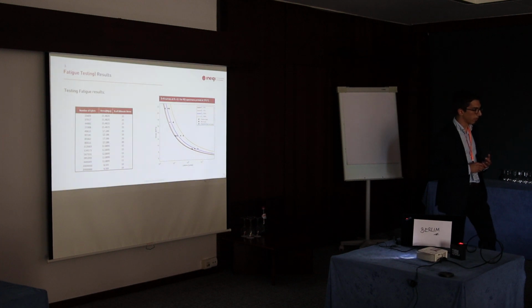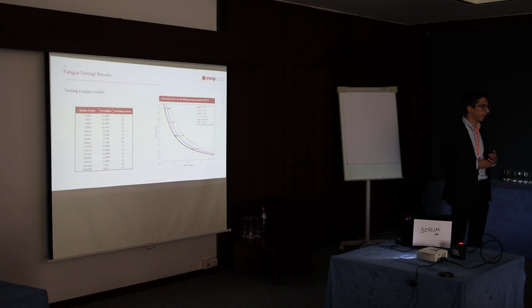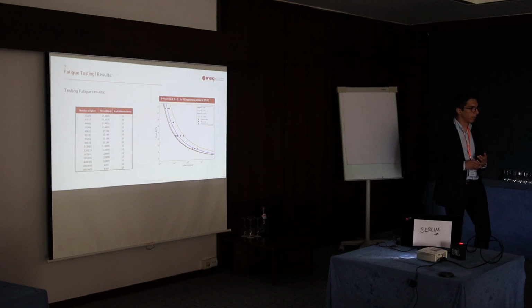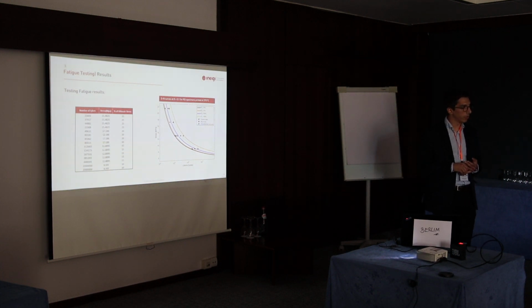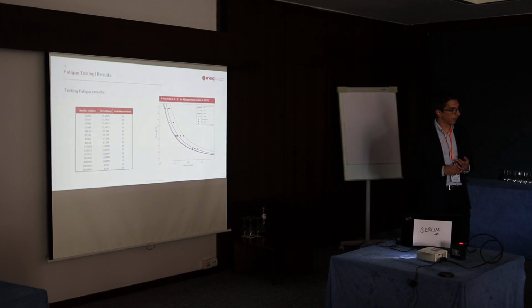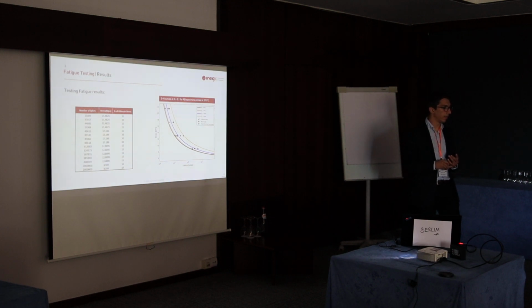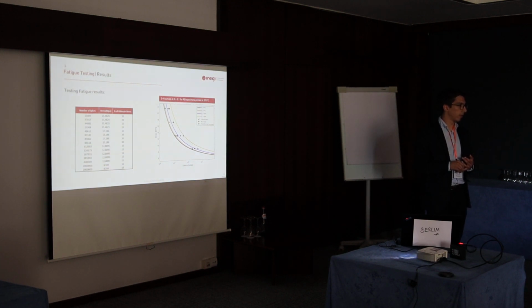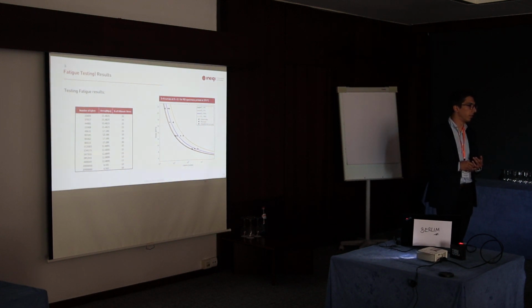It is a well-known fact. I mean, thermoplastics are very frequency dependent when you do fatigue tests. So you suggest that I do? You have to take frequency into account in thermoplastics. Yes, in some cases higher frequency actually increases fatigue life. In some other cases it decreases fatigue life because of the temperature it produces. Okay. So frequency is an important factor. It's not like metals where, regardless of what frequency you test, assuming you don't have much plastic deformation, the results are not very sensitive. But in thermoplastics, they are.